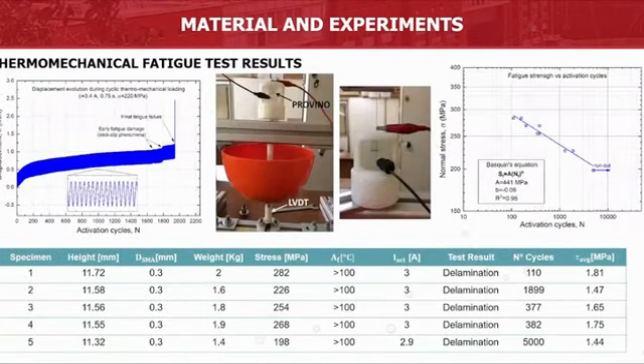Another experimental test was carried out, based on a thermomechanical fatigue test with different load conditions from 200 megapascal up to 300 megapascal, and the specimen was actuated until its complete delamination. The results are plotted on a log-log graph that shows the fatigue strength versus the actuation cycles until the run-out cycles of 5,000, and show a typical behavior of fatigue.